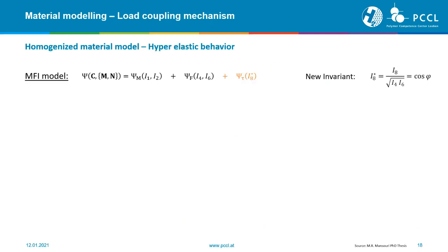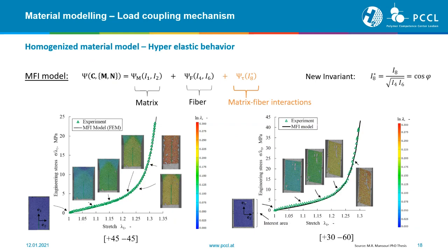And what we're also doing here is developing new material models, especially for composite materials. One aim we are focusing on is, for example, to develop homogenized material models to describe the hyperelastic material behavior. Only to give you a very quick overview, here we have the MFI model. This MFI model describes the matrix behavior, describes the fiber behavior, and additionally, when we think of our material, what I've shown you before, showing this wrinkling effect, then we also have to explain these matrix fiber interactions. And here our simulation group has introduced a new matrix fiber interaction and also a new invariant, explaining this material behavior as you see it here.